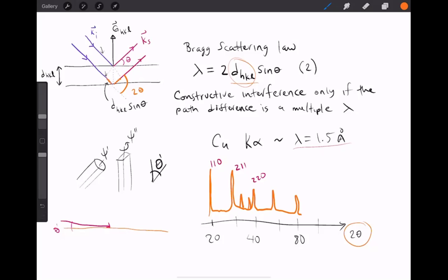Or maybe you're off because your device is not calibrated correctly, and that's what gives you the little bit of difference. But usually you have a different unit cell size, and this peak might not be exactly where it should be, because the database says that this peak should actually be here, and you're off by 0.1 of a degree.